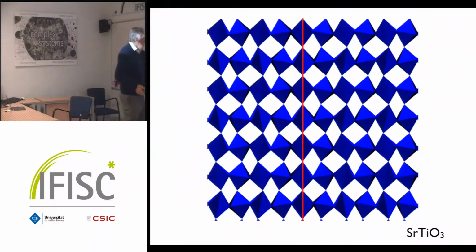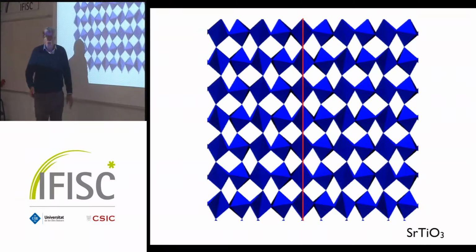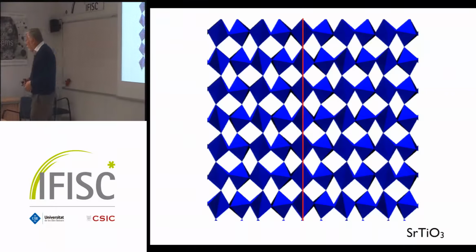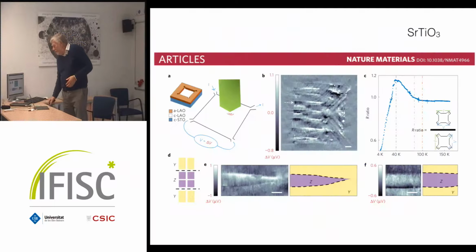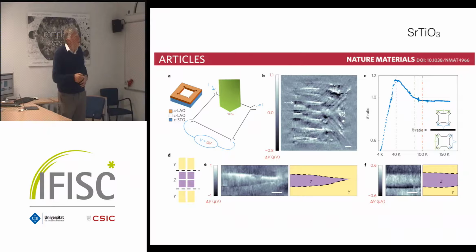And so here, this one would be the untilted octahedra in strontium titanate. And that is the area where the dipole moment comes. And then if you take an interface between strontium titanate and lanthanum aluminium oxide, you get these free electrons. So if you now smear free electrons on top of it, and you do an AFM experiment where you squeeze the entire device up and down, suddenly all the domain structures of strontium titanate come out. I mean, it's like a photographic process, really, when you look at it. I mean, you have this thing, and you don't squeeze it, you don't do anything, it looks perfectly totally uniform.